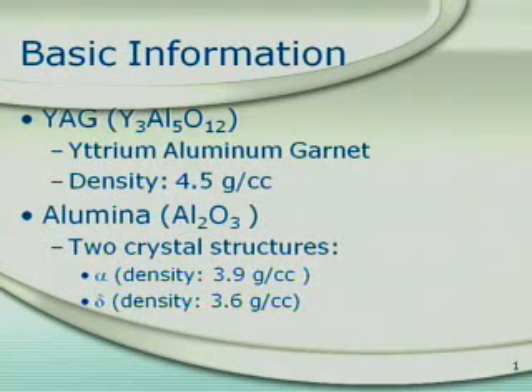The alumina I have been working with comes in two phases, or crystal structures, the delta phase and the alpha phase. The delta phase is a high-temperature metastable phase, often used as a support material for catalysts. The alpha phase, also known as sapphire or corundum, is the stable phase at room temperature and is also used for many optical, structural, and electrical applications. All of these powders are made using a process called liquid feed flame spray pyrolysis, or LFFSP.